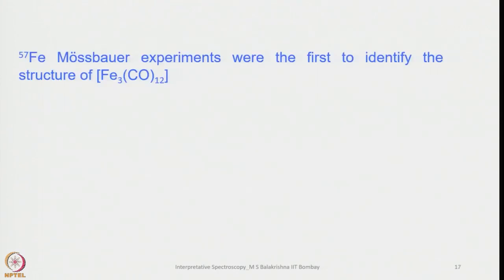57Fe Mössbauer experiments were the first to identify the structure of Fe3CO12. Of course, the Fe3CO12 structure was confirmed by single crystal X-ray diffraction studies. And when you look into IR, IR also shows you the presence of bridging carbonyls, but it would not tell you whether only two have bridging carbonyls and the other one doesn't. That information doesn't come from IR spectroscopy. That is a limitation of that technique.